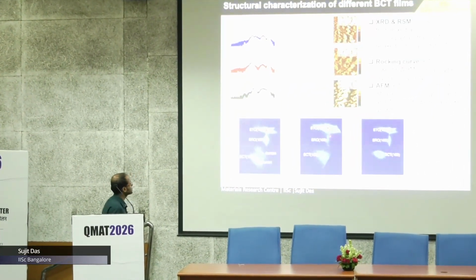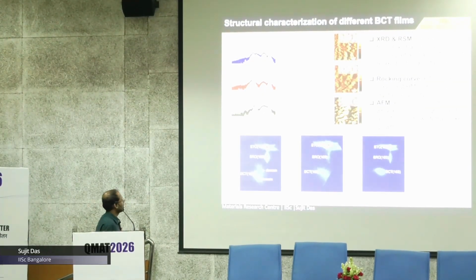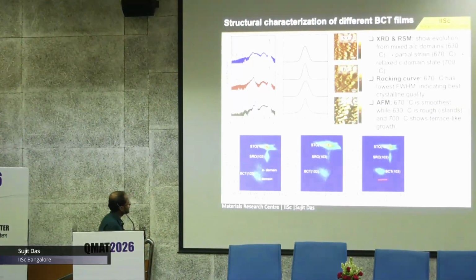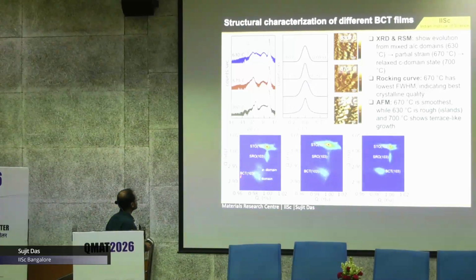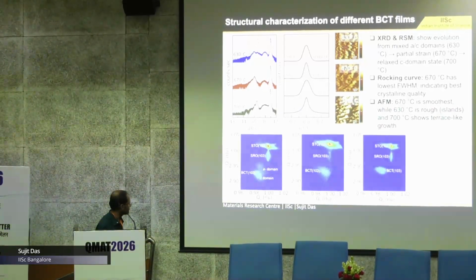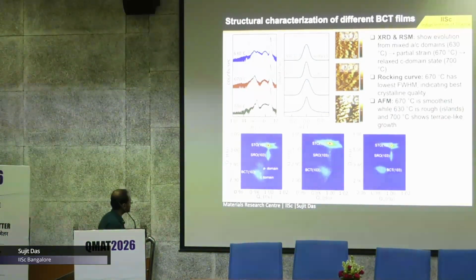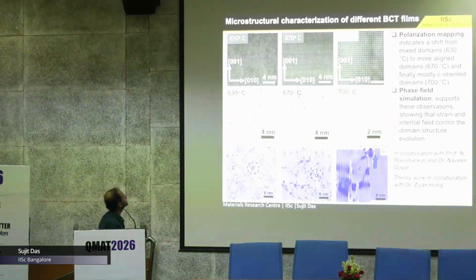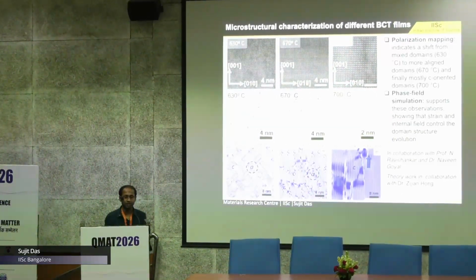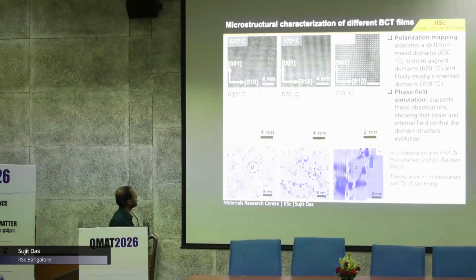Now once we look at the reciprocal space mapping at the 103 reflection, for these materials grown on strontium titanate substrate, we found that all films are relaxed, particularly the film grown at 630 degrees C, which shows peak splitting, indicating there are a-c nano domains. This we further confirm with the TEM and polar mapping.